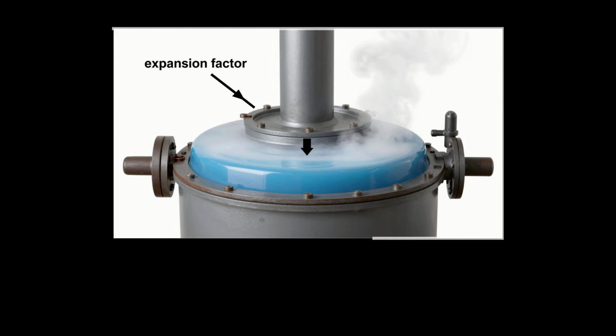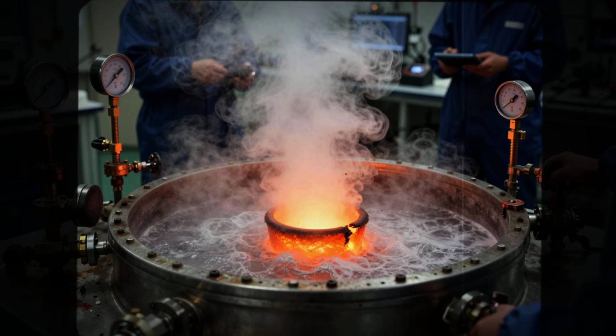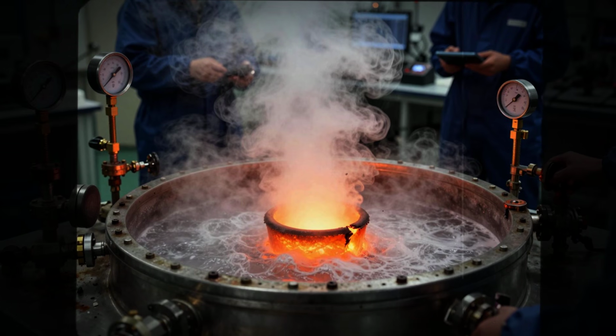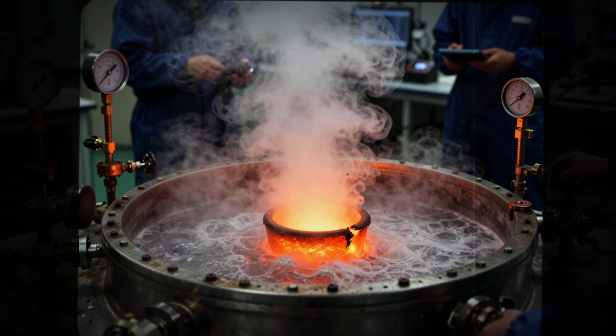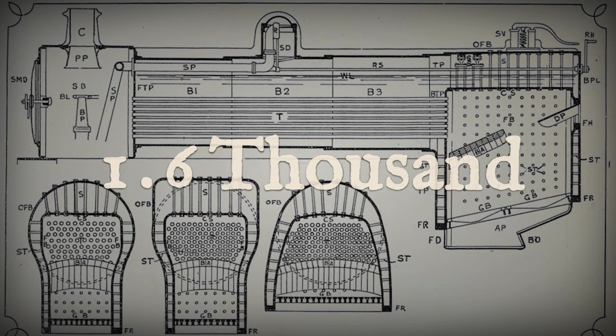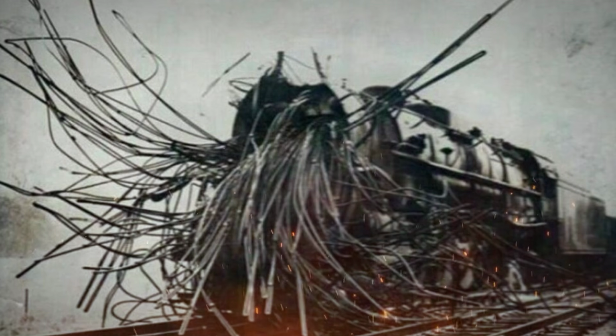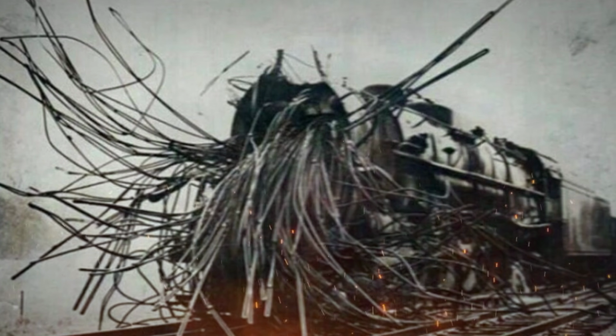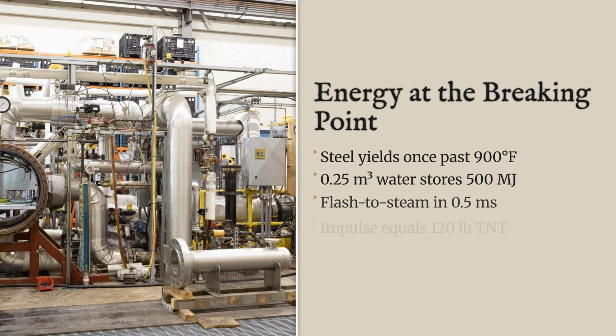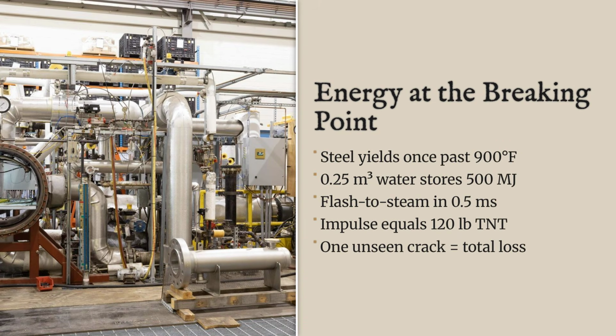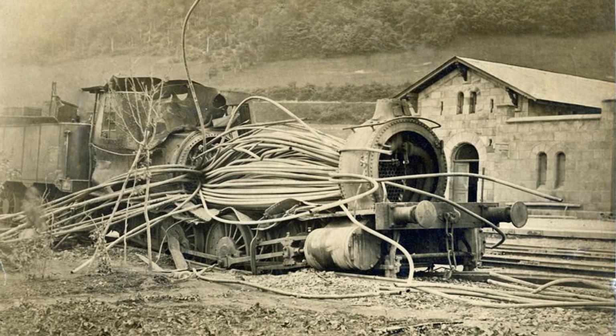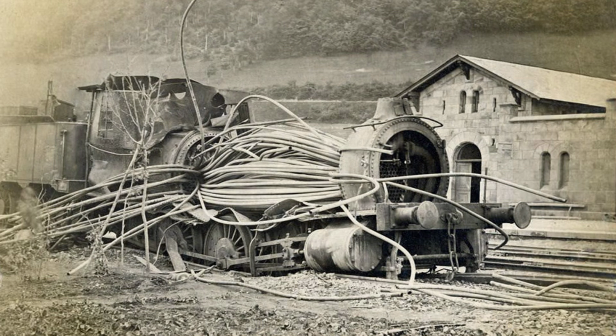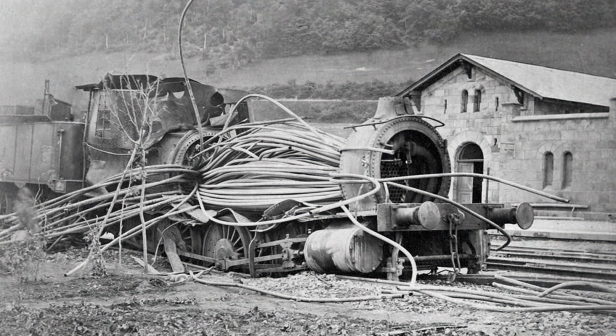Now the expansion factor comes into play. Water under pressure, suddenly exposed to firebox heat, flashes to steam. Volume increases by a factor of 1,600. The energy release is not gradual, it is instant. 500 megajoules of latent heat convert to kinetic force in half a millisecond. The boiler does not leak. It detonates. This is the margin math.